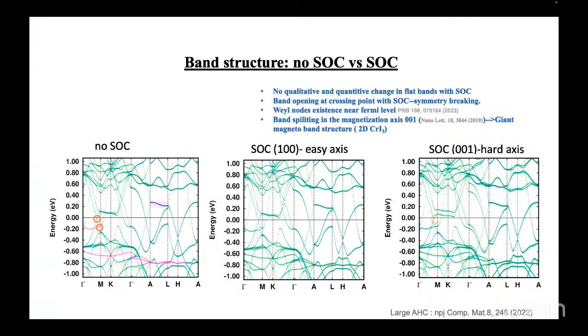So we see a clear difference that as we go from the non-SOC to SOC, we get band openings at the points near the Fermi levels, which are the Weyl nodes, as we compare to the theoretically reported Weyl nodes that were present. And we get the openings of the bands. And as we also change the spin direction from in plane to out of plane, we observe the band structure has also changed.